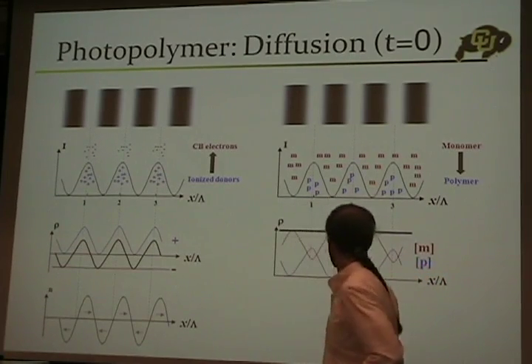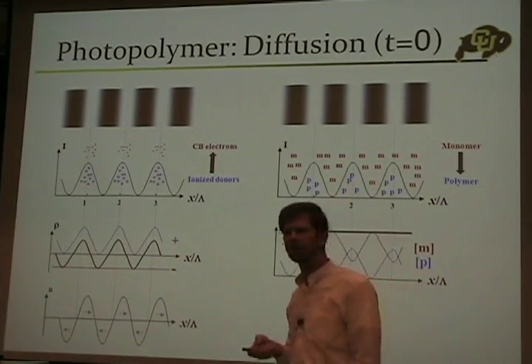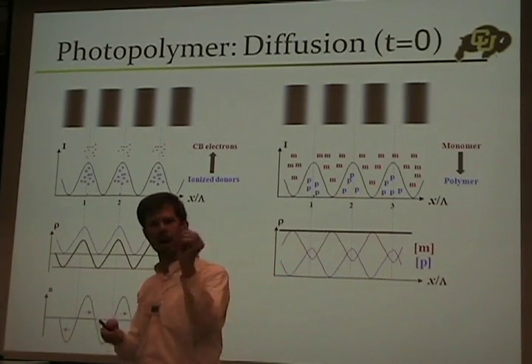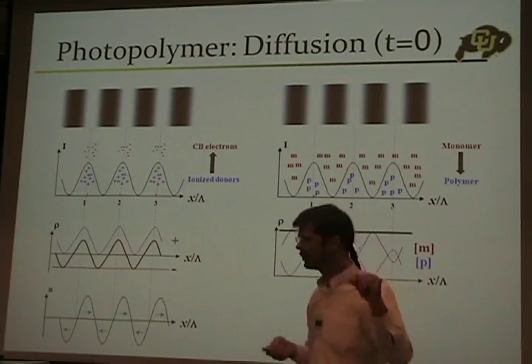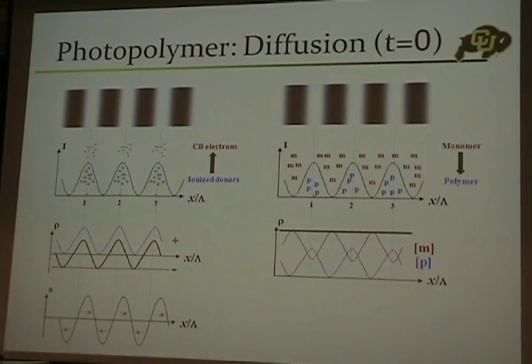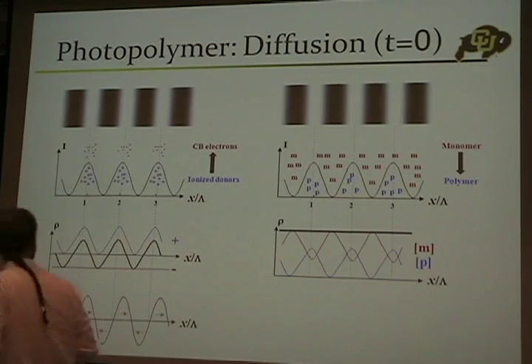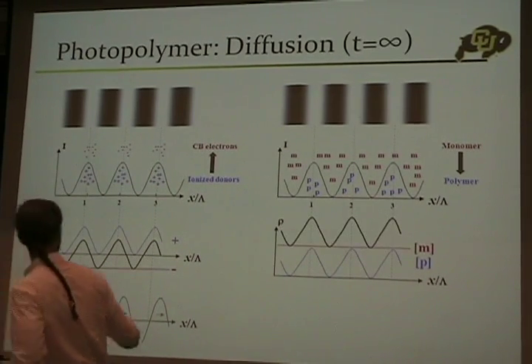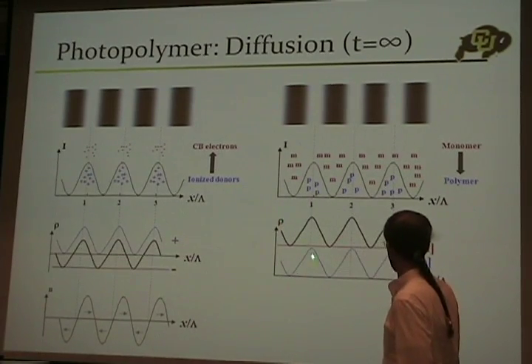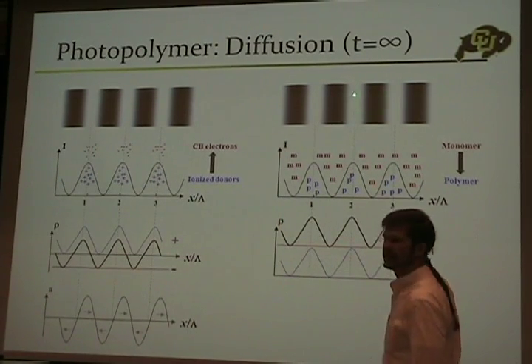Polymer is very rapidly a large molecule — 'poly' meaning many. It could have a molecular weight thousands of times the monomer, depending on how many join up. So it can't move. The monomer, however, is small, and these materials are going to be soft and rubbery. That means diffusion is allowed for the monomer units. So the monomer can move. In an idealized long-time limit where the monomer takes on its average value, suddenly the mass density looks like a copy of the polymer density, which is conveniently a copy of the intensity.